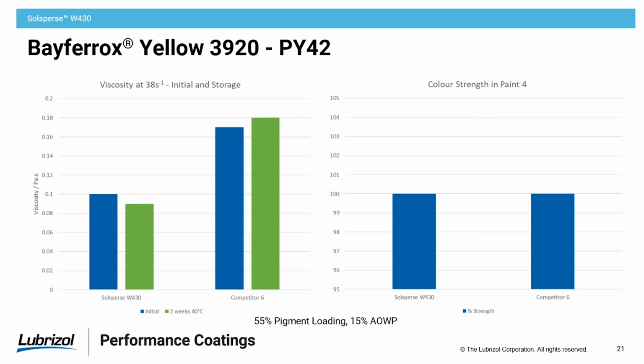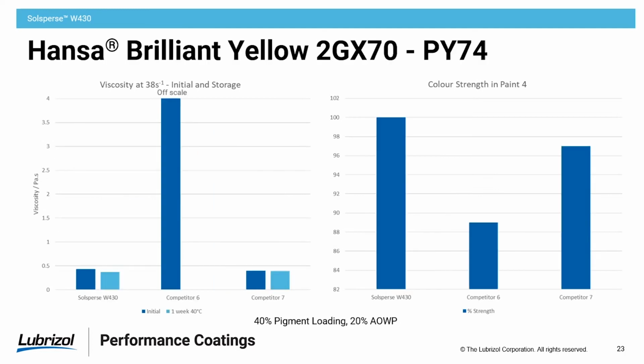And we're with a competitor number 6 here because this was one of the better performing competitive dispersants. A number of the other dispersants we had looked at with the earlier pigments could not achieve the 55% loading at reasonable viscosities. And if you look, this is pretty low viscosity. So our color strength is right on where it needs to be. Our viscosity was lower and the stability was better. So again, a pigment that's not always easy when you're looking across a range of pigments with a particular dispersant.